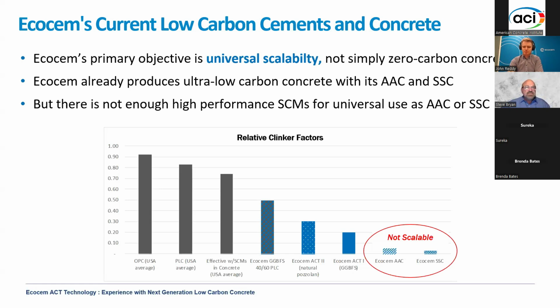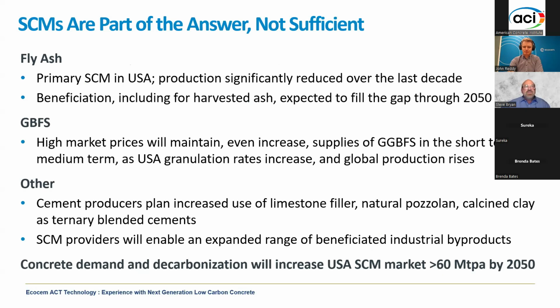As I mentioned, SCMs are certainly part of the answer, but they're not sufficient. We all know that fly ash availability is decreasing, at least fresh fly ash. There is a great effort to use harvested fly ash, which will fill some of the gap. And GBFS is diminishing as blast furnaces are retired in the US and replaced with electric arc furnaces. Although there will continue to be GBFS in the United States for quite a while. It won't be nearly enough, but there will be imports as well as additional granulation capacity installed in the US in the coming years, as the need for decarbonizing cements with these SCMs increases in importance.